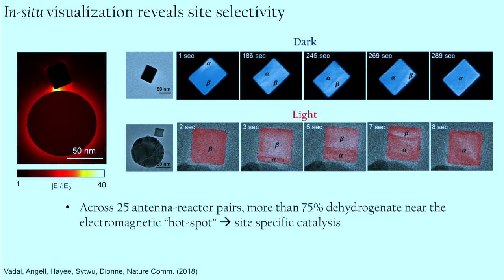So I said that we have those 10x expedited kinetics when we're on the resonance. Here's a calculation of what that resonance looks like. You can see that the local electromagnetic field is very strongly enhanced in the gap between the gold antenna and the palladium reactor. And that's actually where we can better populate some of those palladium-hydrogen orbitals in order to expedite the dissociation kinetics. So this points to the fact that we can get site-specific catalysis, but like I said,